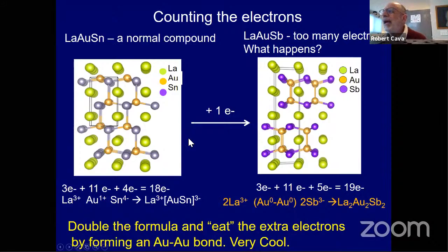But lanthanum gold antimony has one electron more, but something happened to it. The stupid golds bonded to each other. So how did you get a gold-gold bond in anything? So does that mean that one of these golds is a gold minus and one is a gold plus? Or what this is called is two gold zeros. So now, if I want to count these electrons, I can't count this as a gold plus or gold minus in this compound. It's a gold zero.